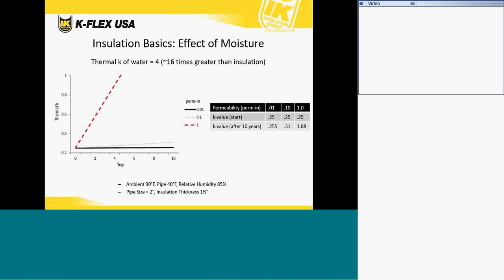This shows exactly what I just mentioned, that a wet insulation system is not going to work as well as a dry insulation system. You can see here, the chart to the right and the graph to the left show insulation systems with various water permeabilities on day one. The solid black line denotes an insulation system that has a permeability of 0.01 perm inches on day one, and shows that since it's such a low permeability material, it will not hold and acquire moisture over the next 10 years, which means that the thermal K that you get at day one, which is about 0.25, will be maintained over the course of the 10 years and really only increase to approximately 0.255, assuming proper maintenance of the system.